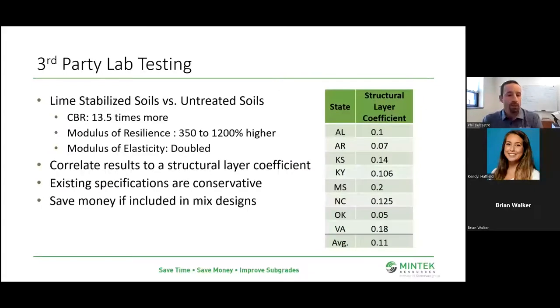So here are some of the numbers I talked about. The lime stabilized soils versus untreated soils see an average CBR of 13.5 times more, a modulus of resilience of 350 to 1200% higher, and elasticity modulus of about doubled. So some great numbers you can kind of get your head wrapped around. These are some pretty good improvements that we're seeing here.